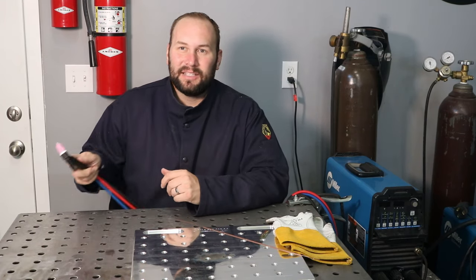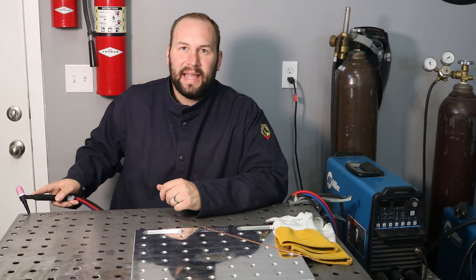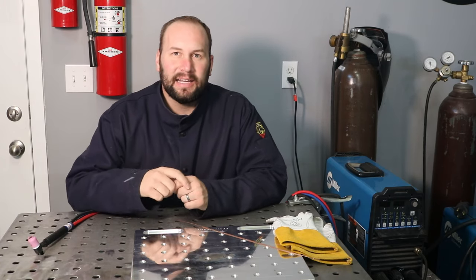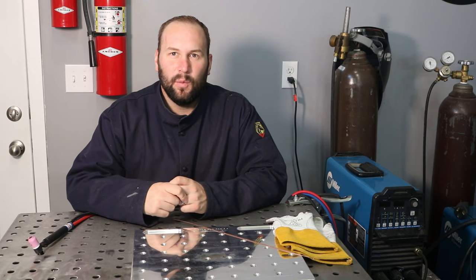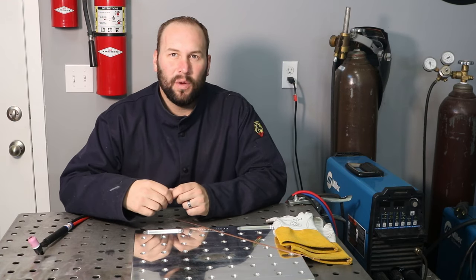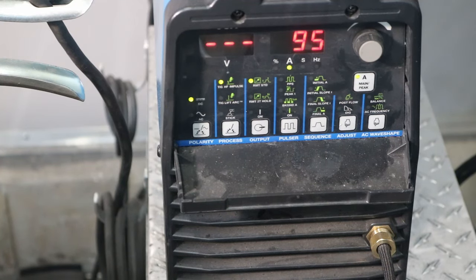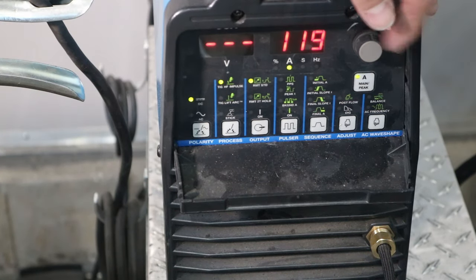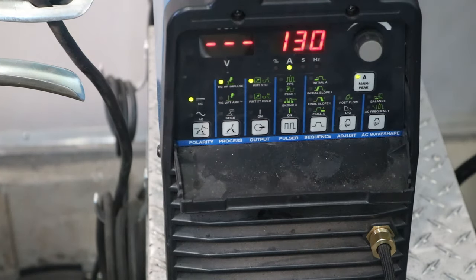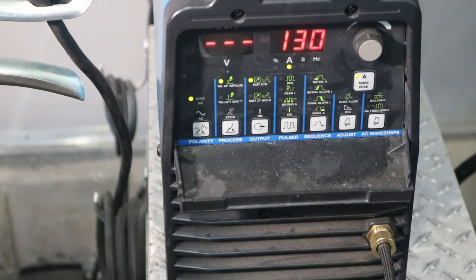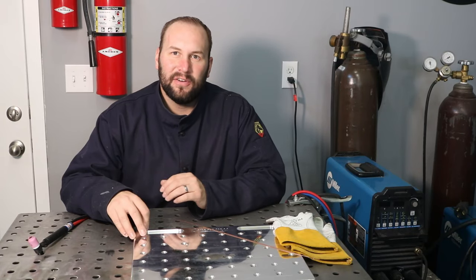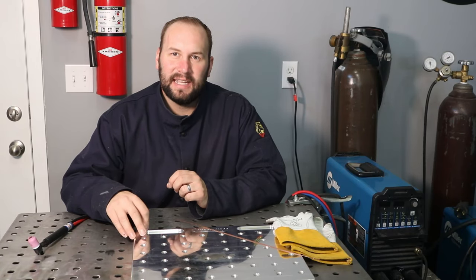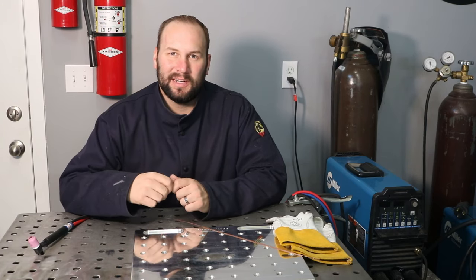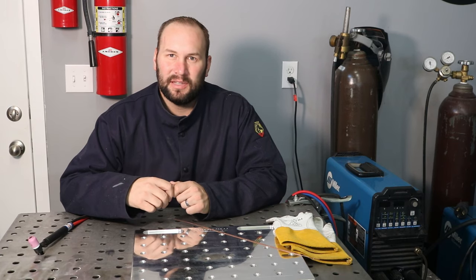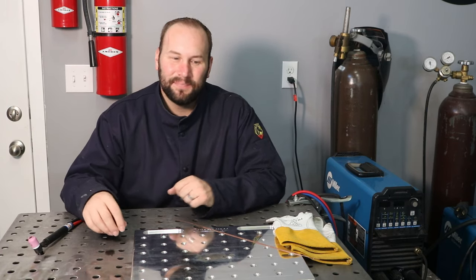Now, as far as machine settings go, we're going to be doing these first exercises on 1/8 inch thick steel plate. And a good rule of thumb for welding is to use 1 amp per 1/1000th of an inch thick, and this works fairly well to get you in the ballpark. So I'm going to go ahead and set my machine to 130 amps, which is a little bit higher since I have a foot pedal. Now, if you don't have a foot pedal, I'd set the machine to about 110 amps if you're working on 1/8 of an inch thick coupons to do these drills that we're going to go over here for learning. And then you might turn it up a little bit when you're actually welding joints and practicing that.